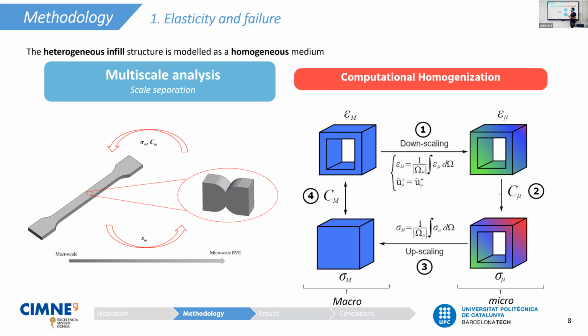The general scheme of the steps to perform this computational homogenization is as follows. We first apply a macro strain field on this geometry. This macro strain is applied in the form of micro displacements. These micro displacements are solved as a standard boundary value problem. We obtain some micro stresses, and then we perform an upscaling, or homogenization, of these micro stresses, obtaining the macro stresses. This homogenization is basically a volume average. And then the ratio between these macro strains and macro stresses is what we call the macro constitutive tensor, which we later use to solve the macro scale.